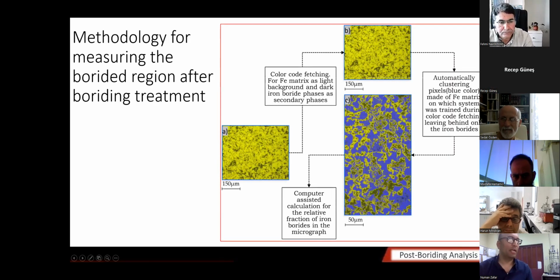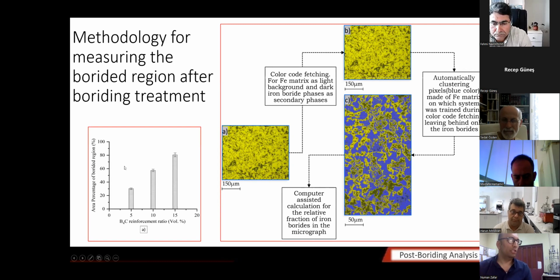Here is a method which I have developed, again using image analysis and color coding, to measure what percentage of a material is borided after using a particular ratio of the reinforcement of B4C particles. This is the methodology. I have already told you it uses color coding, so I will not repeat it. I hope that you have already understood this. So this quantitative image shows that by using 5, 10, and 15 volume % of the reinforcement ratios, you can have this percentage of the material borided, based on these images.